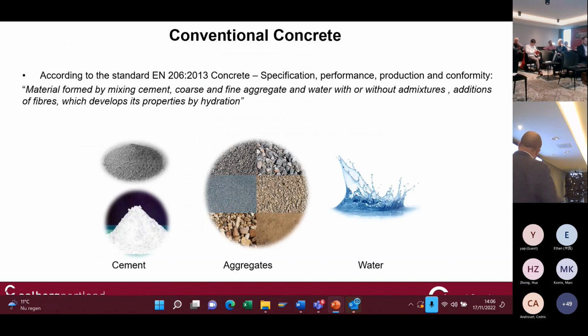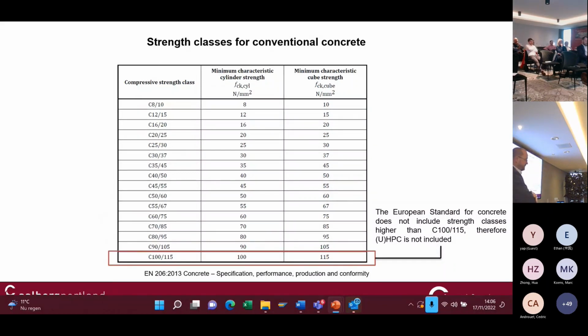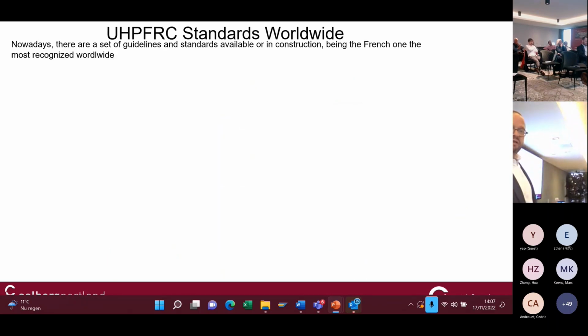So yes, starting from conventional concrete, known by everybody, of course cement plus aggregates and sand and water, we can achieve different strength classes. But the European standard only goes up until strength classes C100/115, meaning 100 Newton per square millimeter for the cylinder strength and 115 for the cube strength. This is a limit that has been passed since the development of high performance and ultra high performance concrete. And so the guidelines for the higher strength classes are still in evolution and still in negotiation.